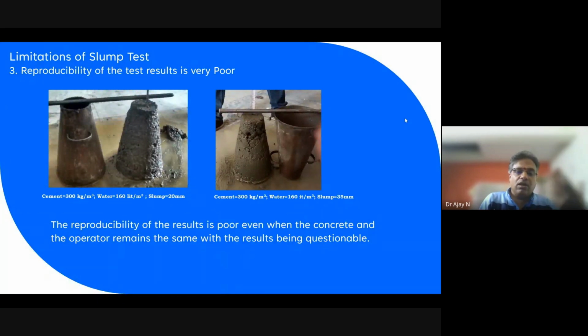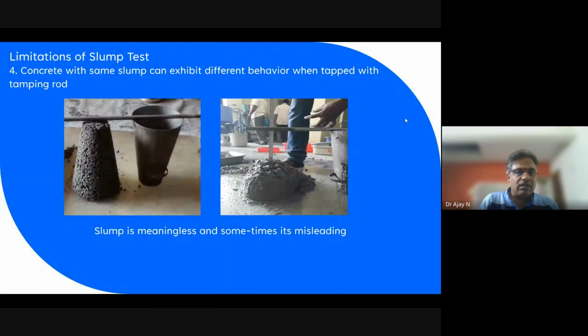And this may depend upon how we operate, and that also comes into the picture. There is no repeatability in the slump test, and we cannot differentiate the mixes. And sometimes, without any tapping, it shows zero slump. When we make a tapping, because of the compaction, the voids get erupted, and it comes down to a 50 to 75 mm slump. So these are the limitations we can see in the slump test mainly. It is not only for low workability, it is also for flowable concrete and highly flowable concrete like SCC.